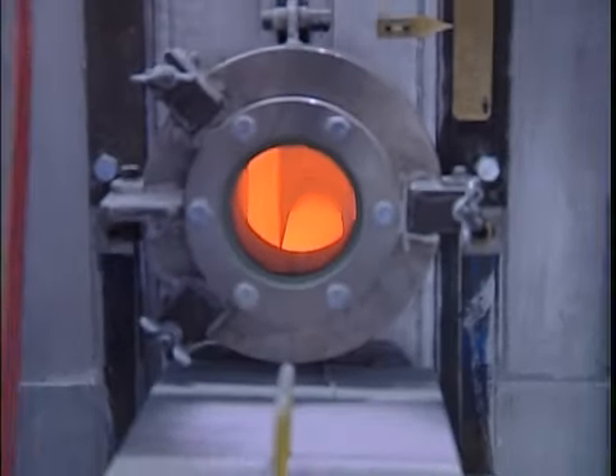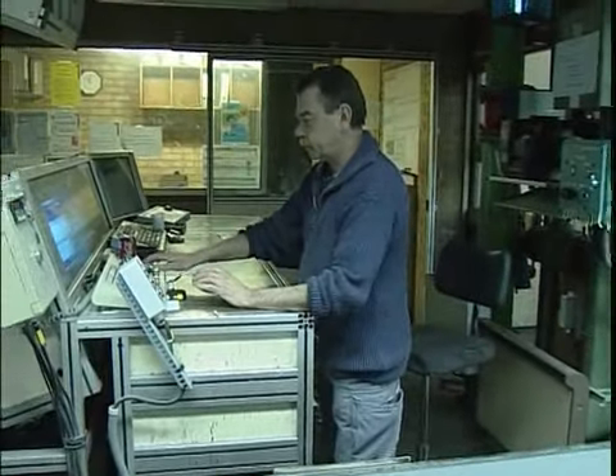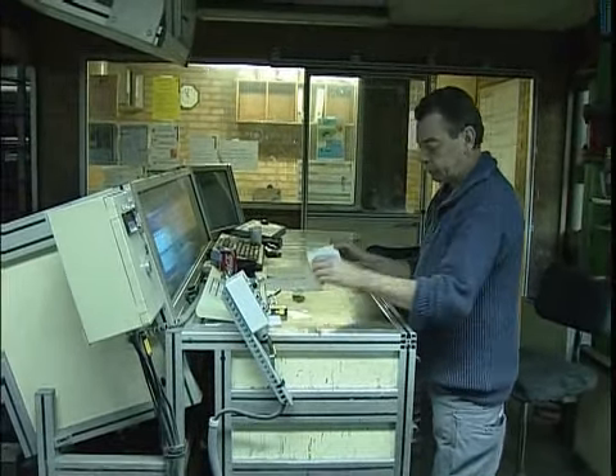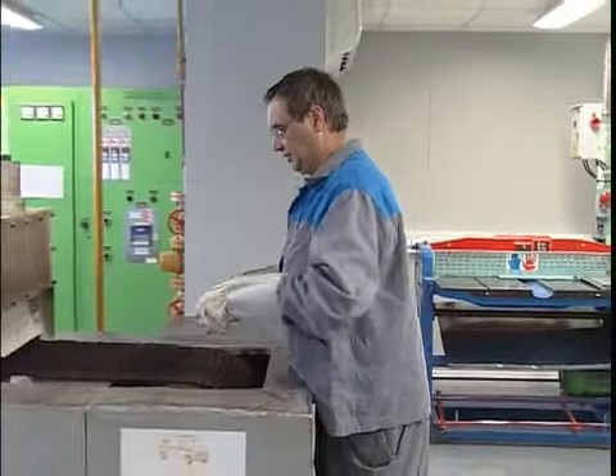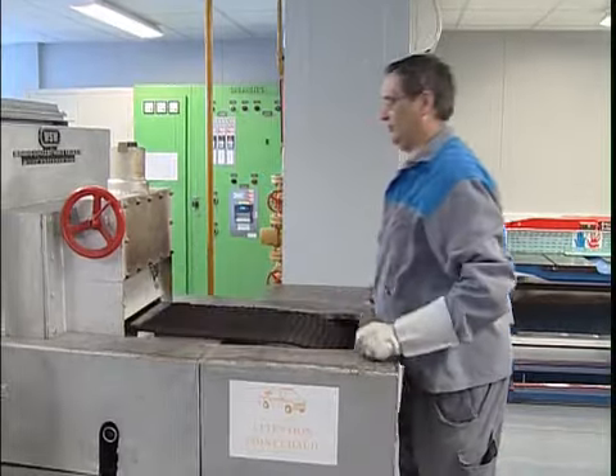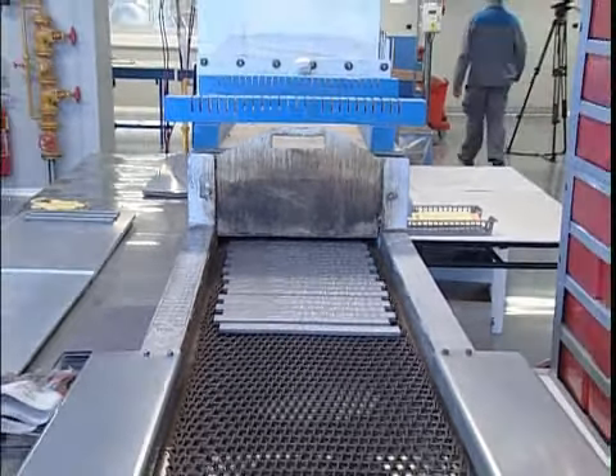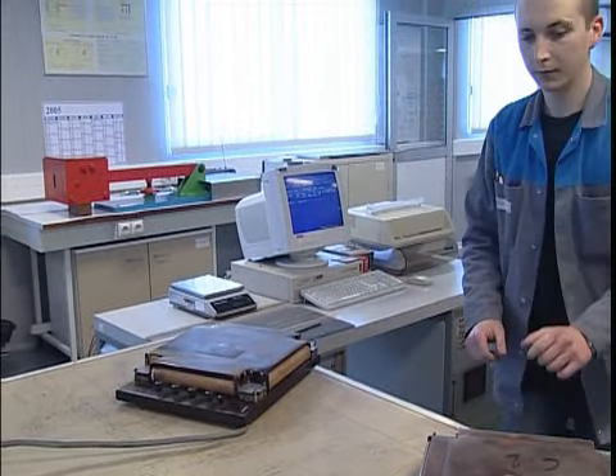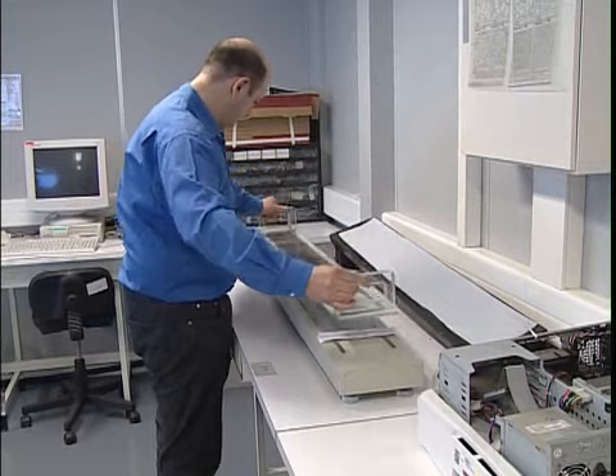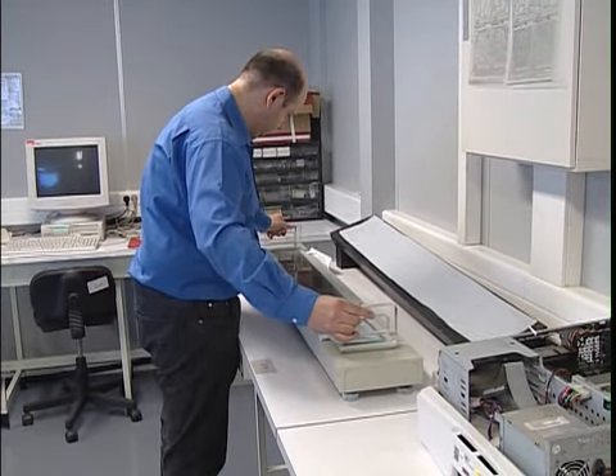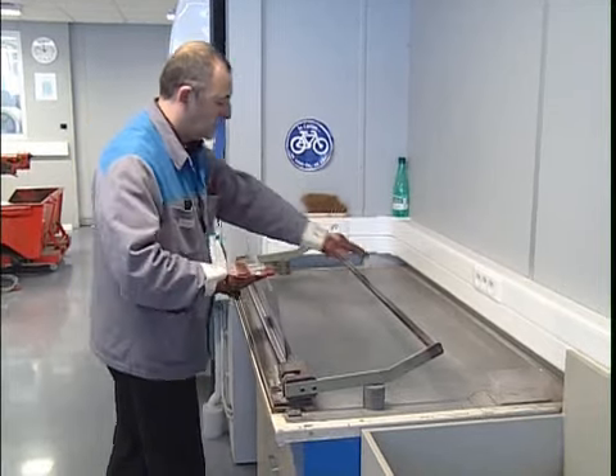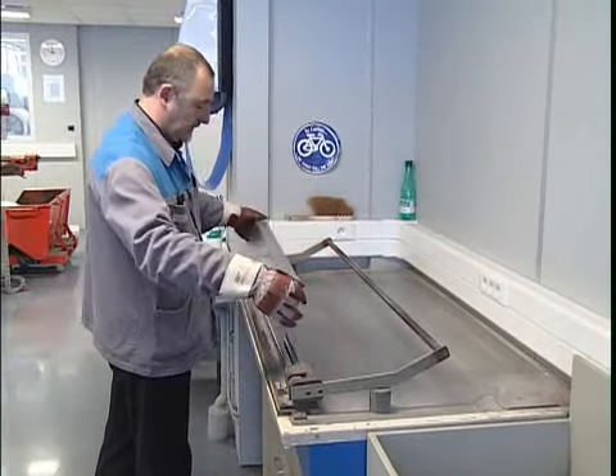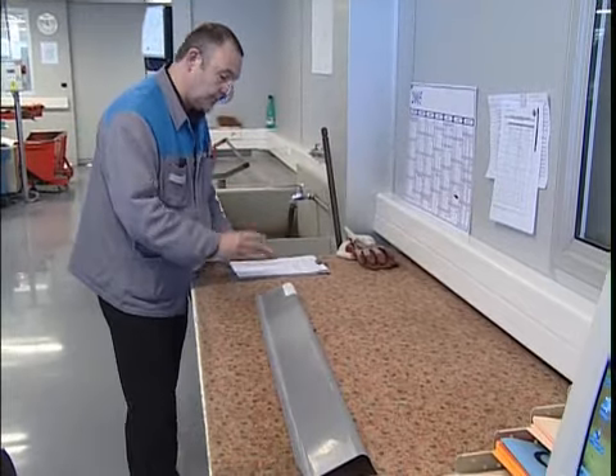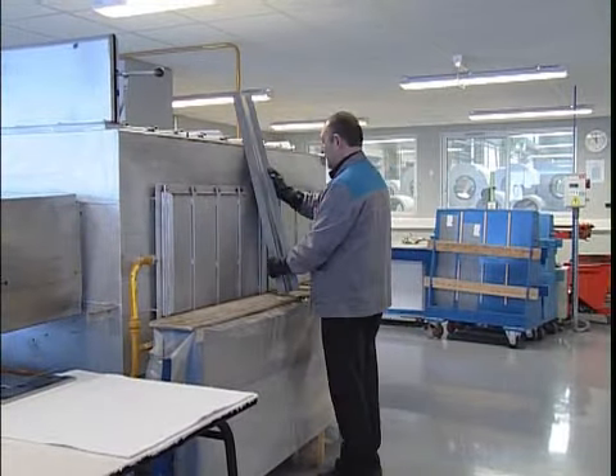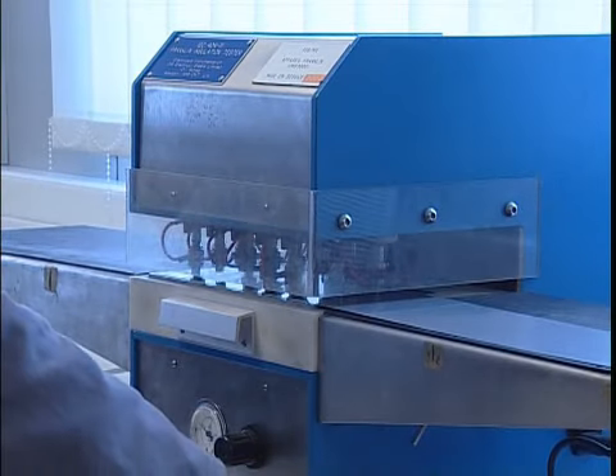Besides numerous online measurements for quality, the inspector at the line takes additional test samples for laboratory measurements. Taking and listing samples, annealing in a continuous furnace, checking the magnetic properties in the Epstein frame, and checking the generated texture of the finished electrical steel by means of a domain viewer. This is the task of the inspector in the laboratory. The inspection of the adhesion of the insulation coating and the ductility of the strip are also part of testing, as is the determination of the insulation coating resistance by using a standard testing method called Franklin tester.